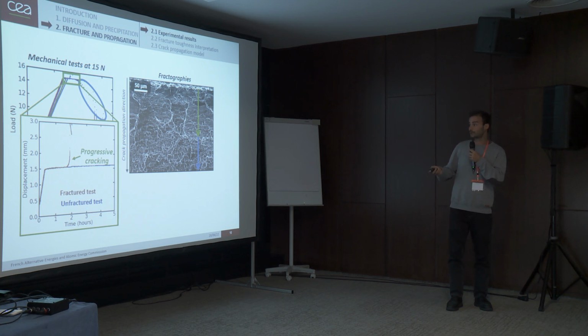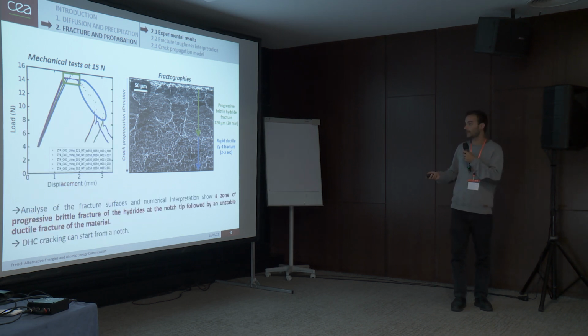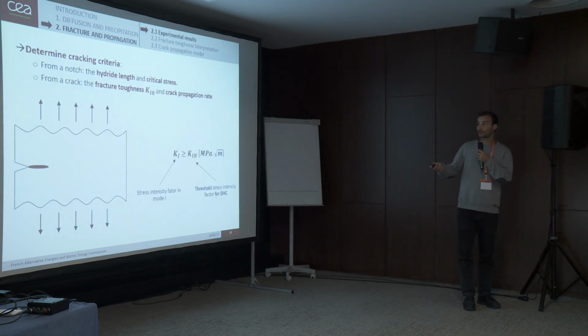So it's a progressive cracking that corresponds to the first fracture mode, which is a progressive brittle hydride fracture. And then here you can see a jump that corresponds to a rapid cracking, which corresponds to the second fracture mode, which is the ductile Zircaloy fracture. Also, we saw that DHC cracking can start from a notch and not only from a crack. So, as I said in the beginning, we wanted to determine the cracking criteria.